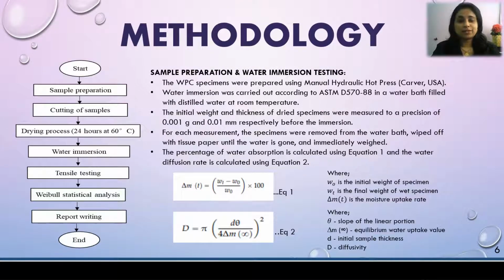The methodology of my project is as shown in the diagram in this slide. The WPC specimens were prepared using a manual hydraulic hot press with an open mold and then cut into the desired dimensions. Then, all the specimens were dried for 1 day at 60 degrees Celsius before the water immersion testing. Water immersion was carried out according to the American Standard for Testing and Materials as stated in this slide, in a water bath at room temperature.